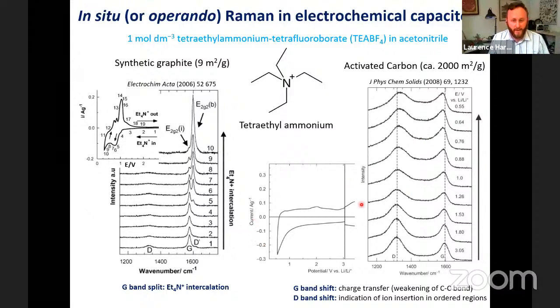So you see also electrochemically, your response is very different to synthetic graphite, but also the spectra are very different. The spectrum you measure for different types of carbons does vary depending on its crystallinity. And so you don't see a very nice splitting, but instead you see subtle shifts of these two main bands, the G and the D band of the carbon. Essentially, the G band shift can be associated with a charge transfer onto the carbon sheet, and then the D band shift could be an indication of ion insertion into some of the ordered regions within this type of activated carbon. So you can use spectroscopy to understand what is happening at this electrode interface.